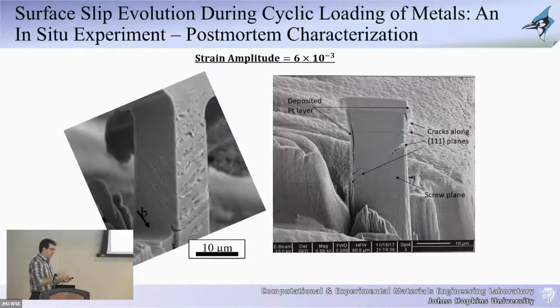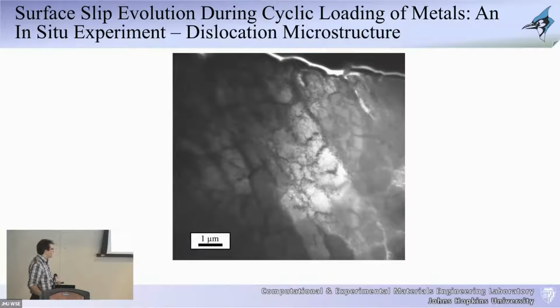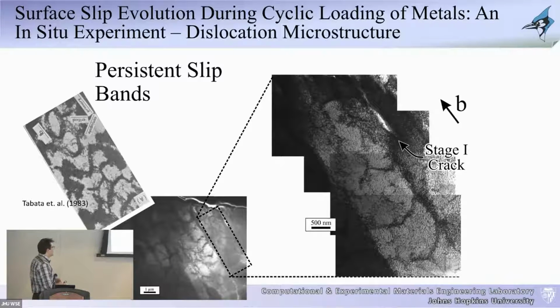Now, the reason that a lot of this community in the small-scale world did not necessarily try to go down that length scale is that a lot of people would argue that whatever behavior you're seeing at these length scales, which is still quite large, 10 microns to me is quite large, typically people argue that there is a significant amount of size effects and the deformation mechanisms are different. What we showed with these experiments is that actually is not true. The exact same type of formation of persistent slip bands, the type of crack propagation along the outer boundaries of these persistent slip bands, is very similar to what you see with these types of dislocation microstructures that are observed at bulk scale. These are the classical bulk scale experiments that people understand in the world of deformation of fatigue.